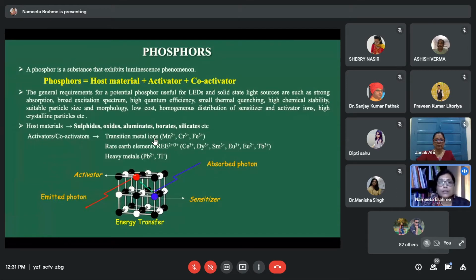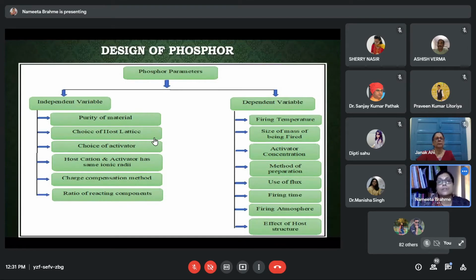Now, one thing is how we design the phosphor. There are different phosphor parameters, where there are independent variables and dependent variables. For example, independent variables: the purity of the material, how pure the raw material we take. Then I am discussing the choice of host and choice of activator further. The host lattice is an independent variable, and then there are dependent variables, because if you choose a silicate material, then the firing temperature depends on that, because you have to fire at a higher temperature if you want to make silicate. So the firing temperature, the size of the batch being fired, activator concentration, and method of preparation are all dependent variables for the design of the phosphor.